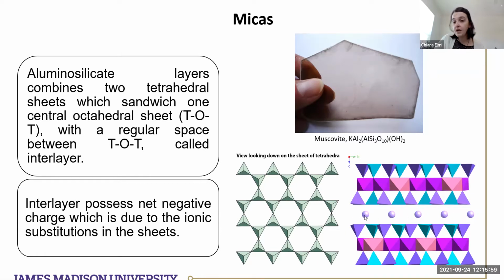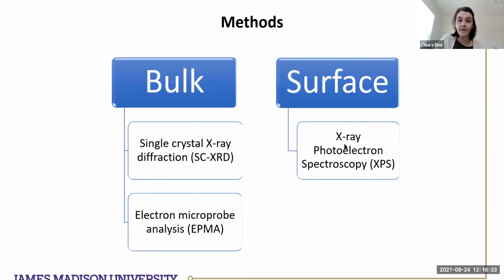But if you see here, you have van der Waals bonds in this spot. So you can imagine that as you have ionic bonds in the TOT, the splitting of the layers will be along the interlayer. Okay, so this is the structure of micas, and that's the mineral that we are going to study. In this example, you see here a set of layers of muscovite.